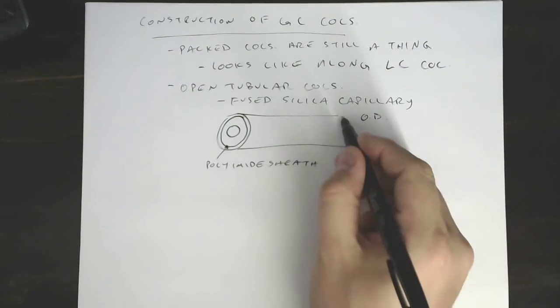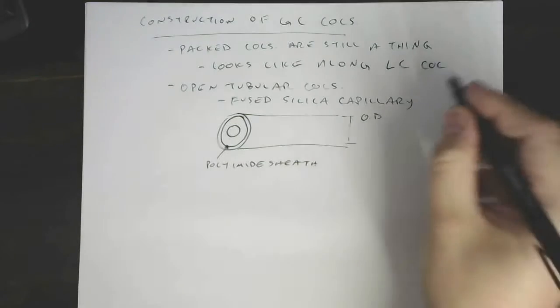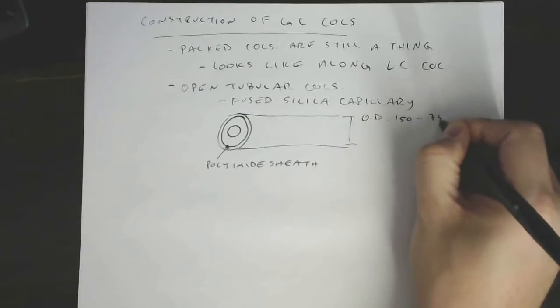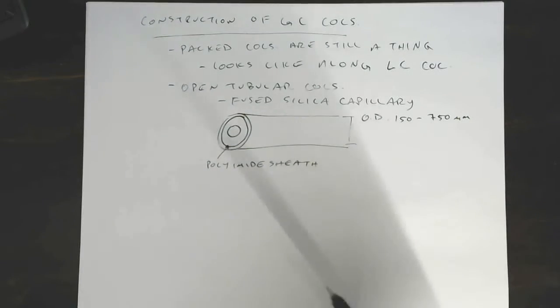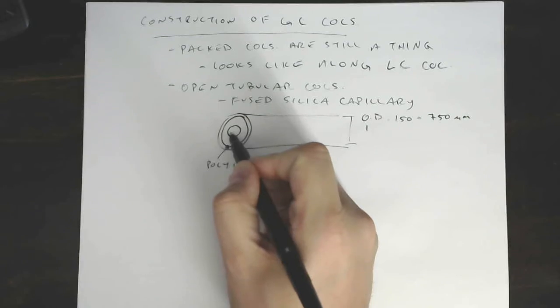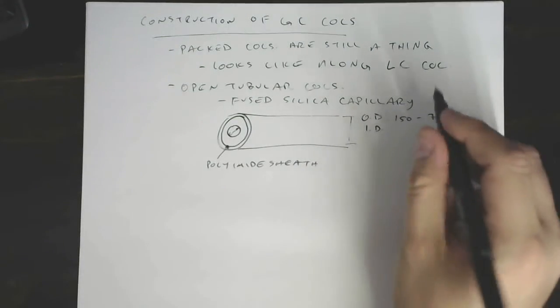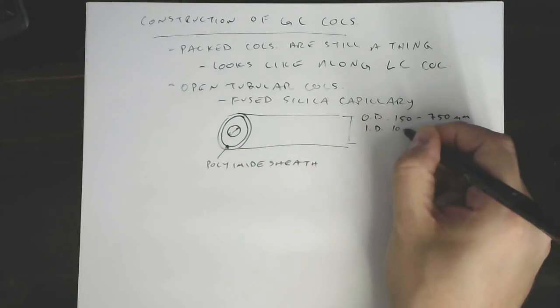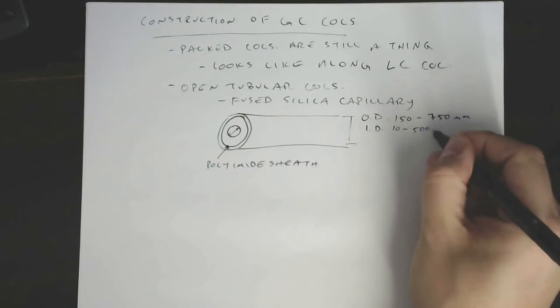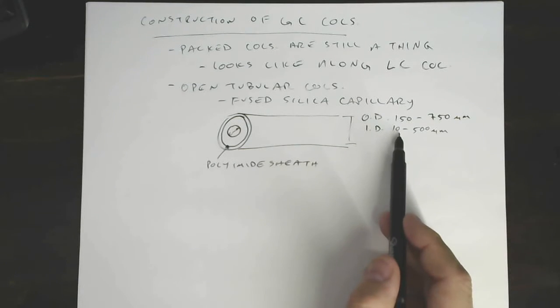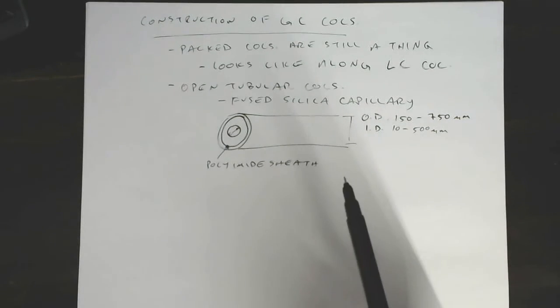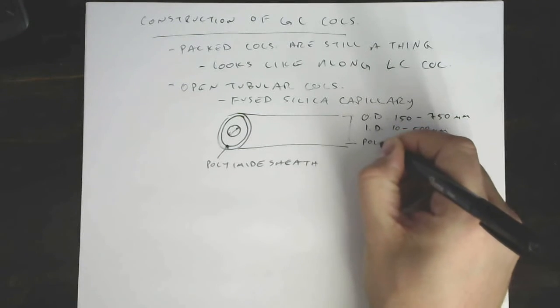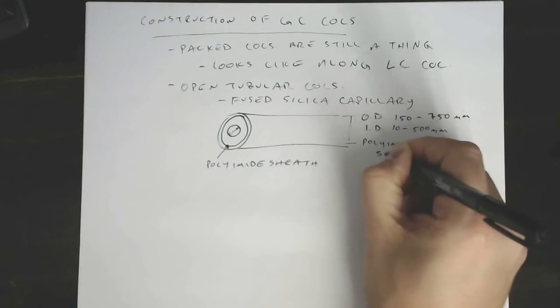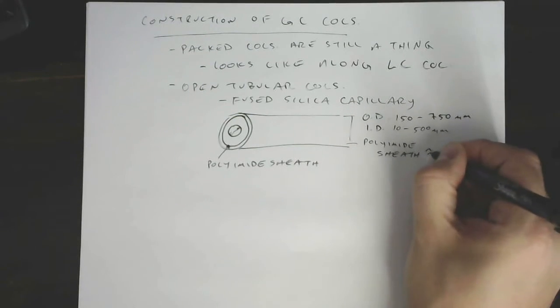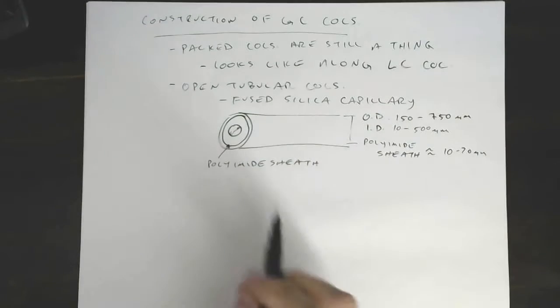So let's talk about the outer diameters. So that would be this dimension here. Outer diameters are typically on the order of, we'll say, 150 to about 750 microns. So these things are smaller than a millimeter usually in outer diameter. The inner diameter, that's this dimension here, can range anywhere from really small, we'll say 10, all the way up to pretty big, 500 microns. And I'll tell you that we're going to talk about capillary electrophoresis a little bit later in the semester. For GC, we are generally on the higher end of this range. And finally, the polyimide sheath. It usually has a thickness on the order of 10 to 20 microns thick of this polyimide coating.